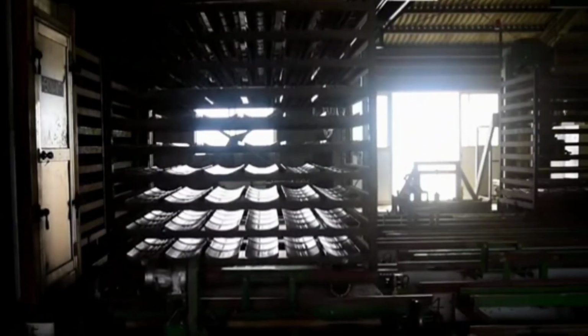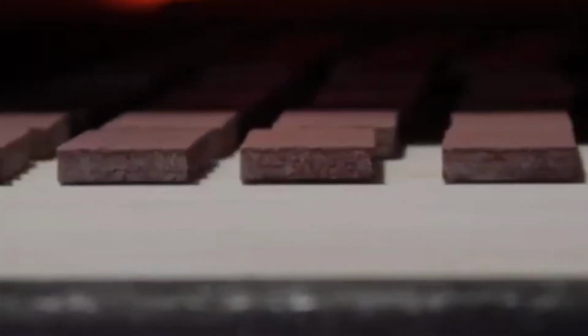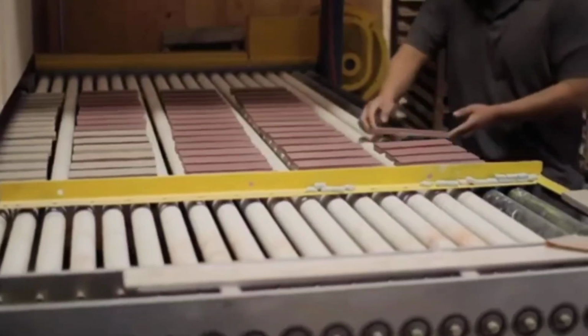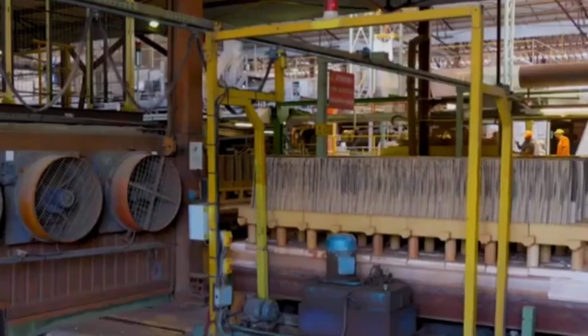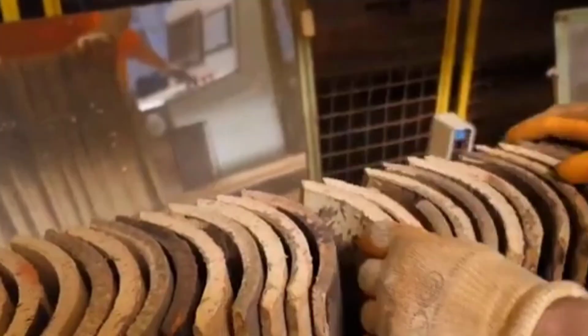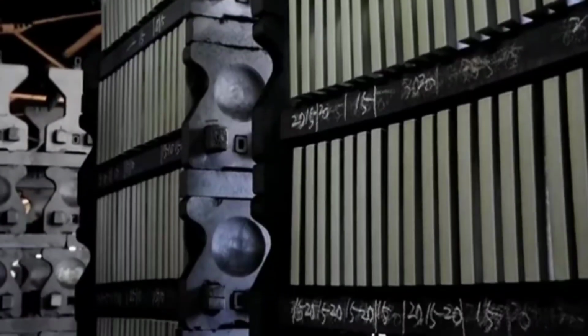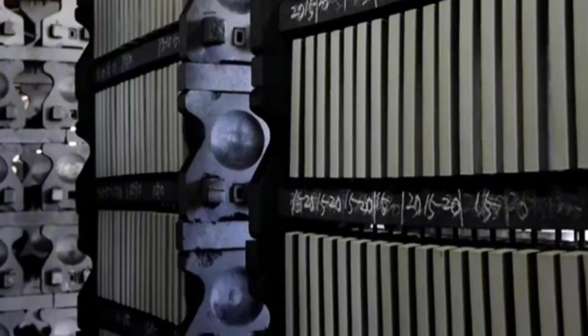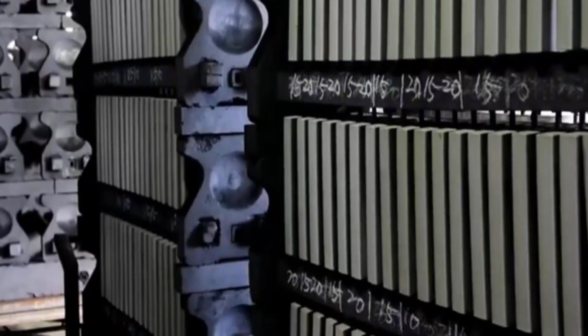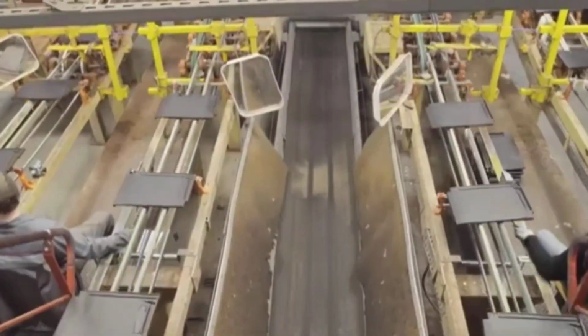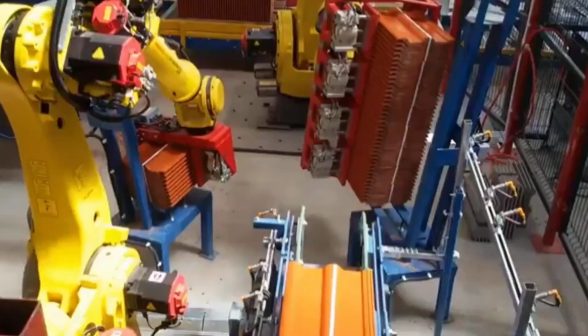Once removed from the kiln, each roof tile undergoes a rigorous inspection to ensure it meets both technical and aesthetic standards. Workers carefully examine the surface for glaze defects, such as peeling, discoloration, or pinholes, while also checking shape, curvature, and dimensional consistency. Specialized gauges are used to measure warpage and thickness, comparing the results to design specifications.